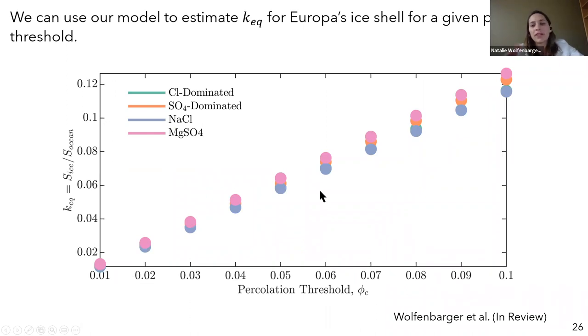And you can see that this is fairly linear as well, but also importantly, not super sensitive to composition either. You end up getting deviations as you get to this higher critical porosity governing your percolation threshold. But this lent credence to both this approach and this idea of using a percolation threshold to constrain what we expect that bulk ice salinity to be. And so although we have 0.05 as a percolation threshold for sea ice on Earth, it's very possible that in the slow growth conditions expected at Europa, the actual morphology of this ice ocean interface can slowly evolve to something that's a little more planar. And the effect of that will be reducing this percolation threshold.